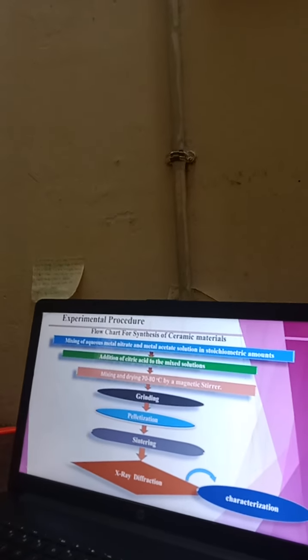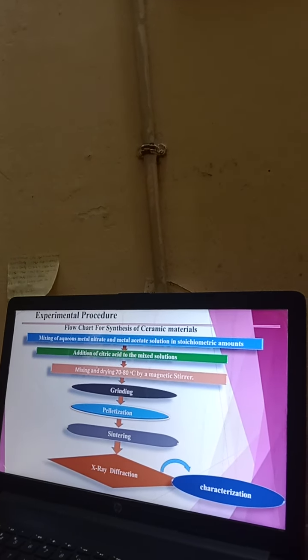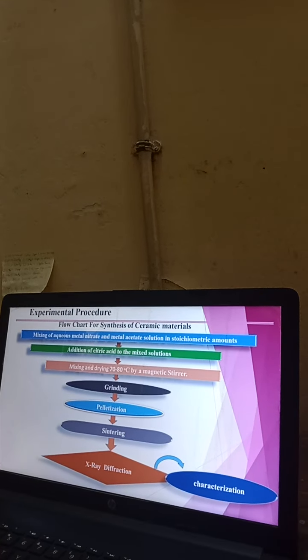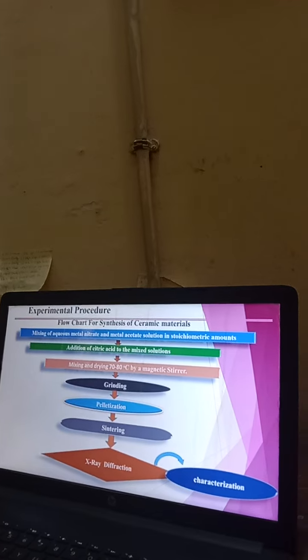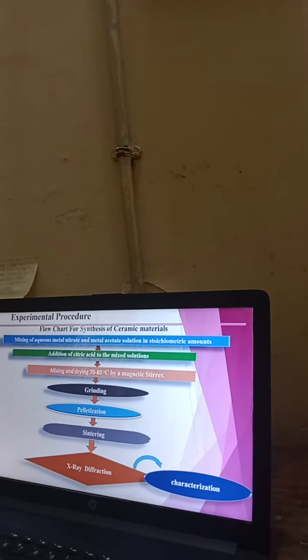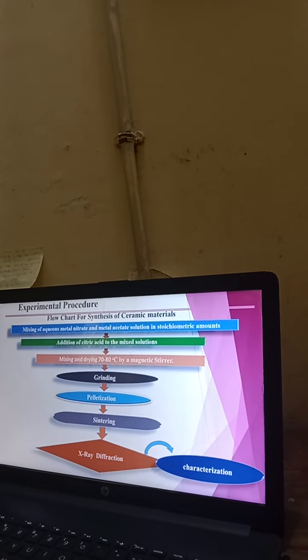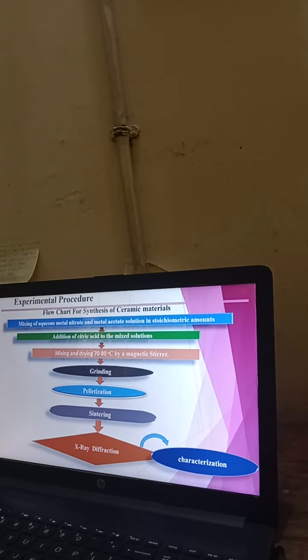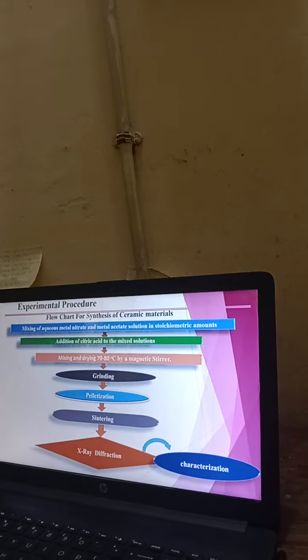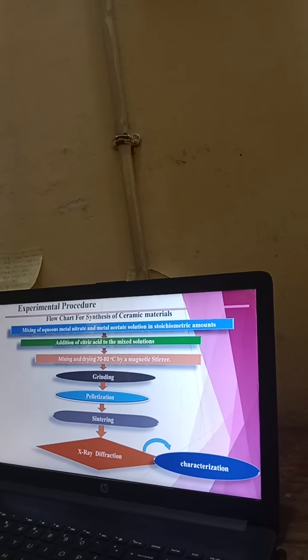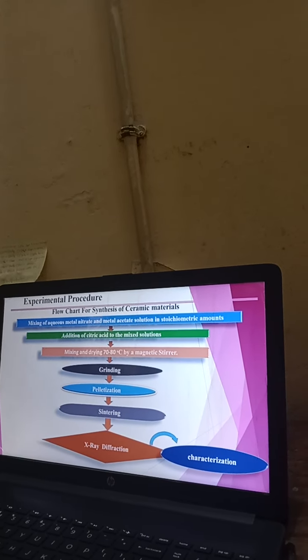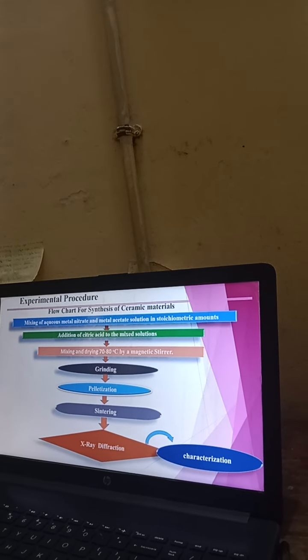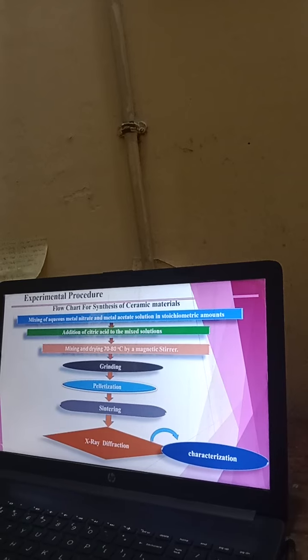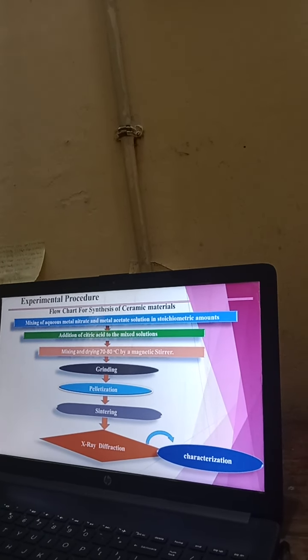This is the experimental procedure and the way in which we have synthesized the materials. This slide shows the flow chart of the synthesis of the ceramic material. First of all, we took the stoichiometric amount of metal nitrate and metal acetate in a beaker in which water was already present, and a separate solution of citric acid was also added. We heated the whole solution on a magnetic stirrer for 24 to 30 hours at 70 to 80 degrees centigrade. After that, we obtained the dry material, which underwent grinding to obtain a fine powder. The fine powder underwent calcination at 800 degrees centigrade for 6 hours.